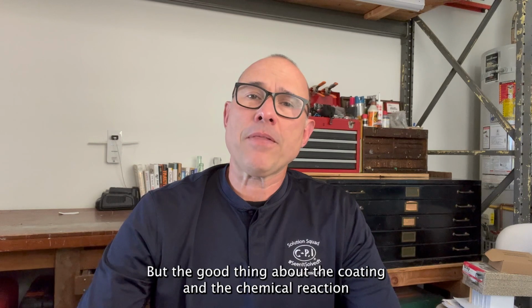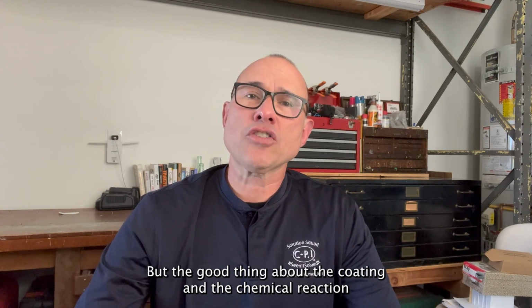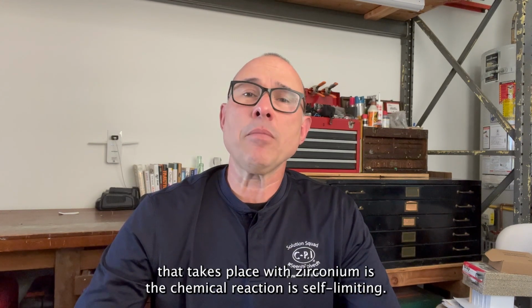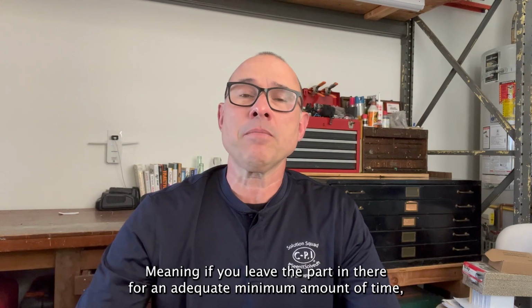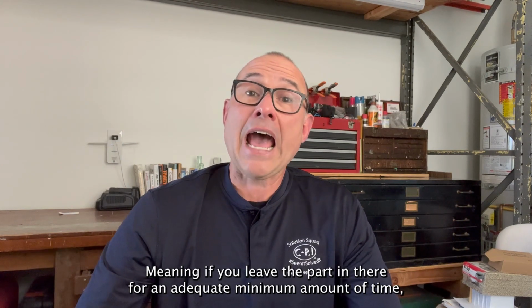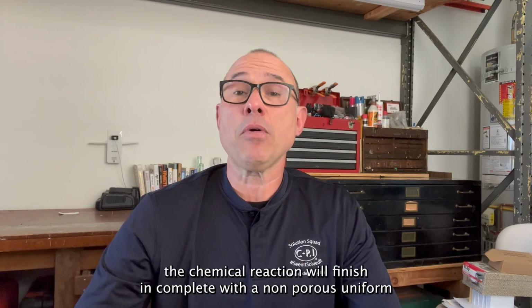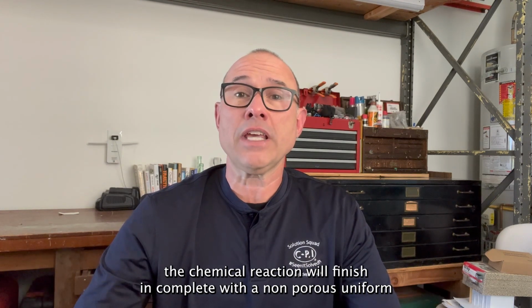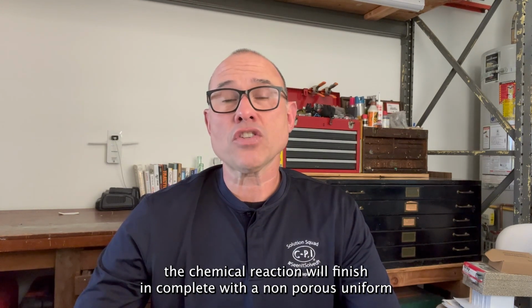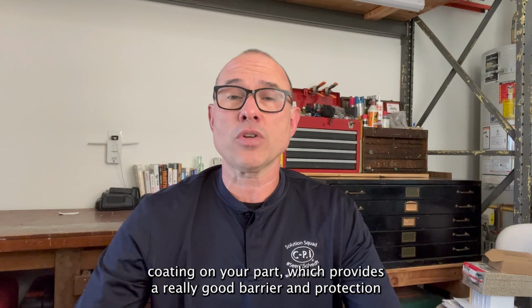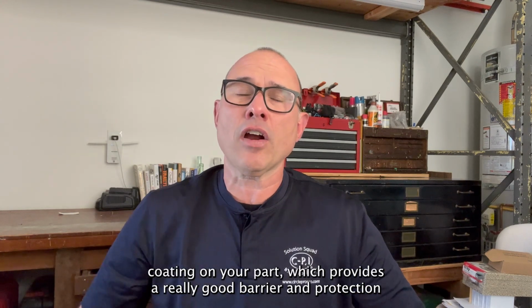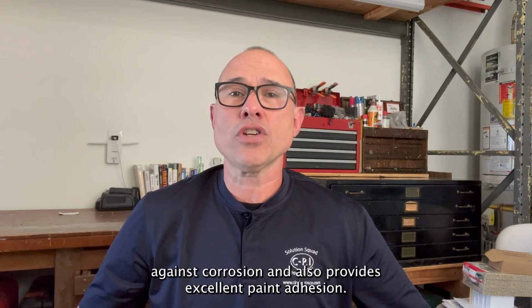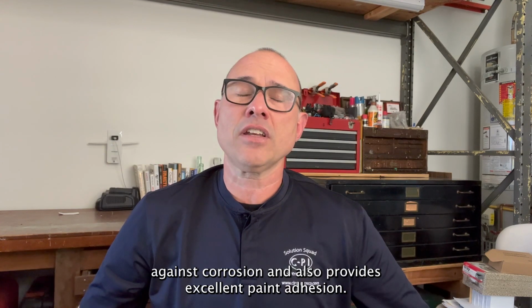But the good thing about the coating and the chemical reaction that takes place with zirconium is the chemical reaction is self-limiting, meaning if you leave the part in there for an adequate minimum amount of time, the chemical reaction will finish and complete with a non-porous uniform coating on your part, which provides a really good barrier and protection against corrosion and also provides excellent paint adhesion.